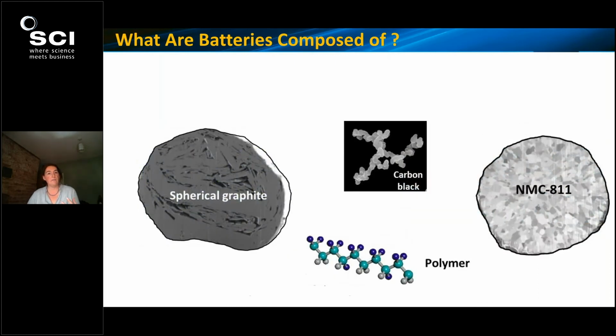And then inside the batteries, we have what we call the active materials. So these are particles of certain chemistries that will reversibly store the lithium atoms. Since 1991, graphite has been the anode active material of choice because it becomes active with lithium ions at lower voltages. On the right, this is a nickel manganese cobalt oxide. It's a sort of micron-sized aggregate of lots of sub-micron grains, and this is a typical cathode material of current commercial interest.